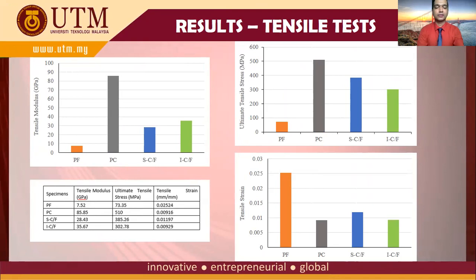Here is the summary of the result and the average value for all the specimens. For the first property, which is tensile modulus, as expected, pure carbon obtained the highest tensile modulus, which is around 85 GPa, and the lowest is pure flex, which is 7.52 gigapascal. We can see the reason why there is a need for hybridization. This is because it could improve the tensile modulus, which is sandwich-like stacking sequence 28.43 gigapascal and intercalation stacking sequence equal 35.67 gigapascal.